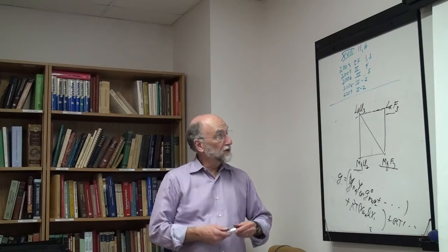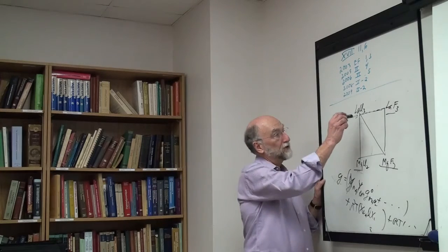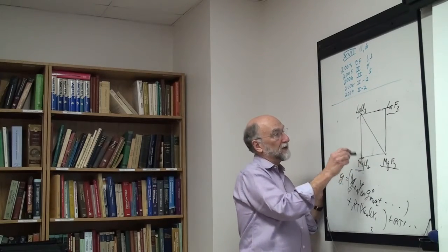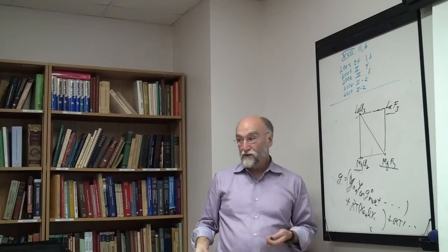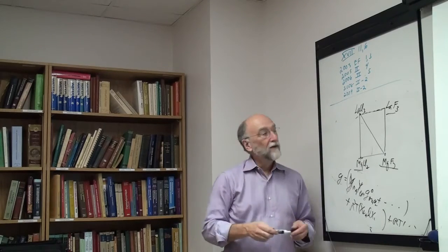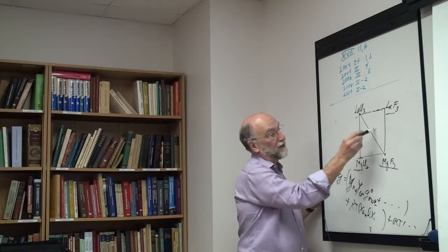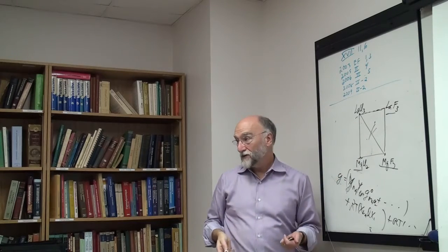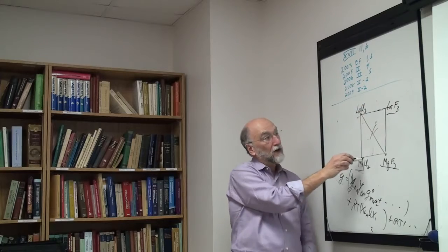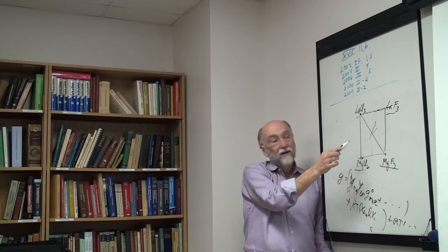Okay. And you're using the sublattice model. You cannot possibly treat this ternary system like an A, B, C alloy system, because it's not at all the same model. And this is not a ternary system. You can have tie lines that cross the boundary quite easily.